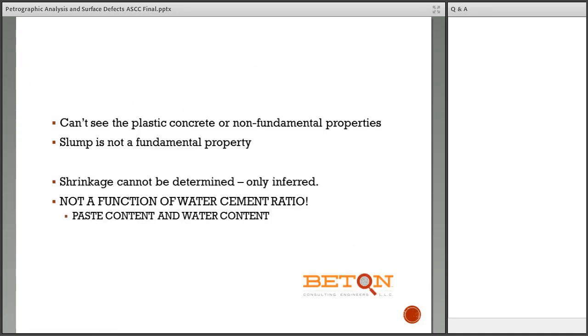So, one thing that the petrographer absolutely cannot do is tell you plastic or non-fundamental properties of the concrete. A perfect example is the slump. Slump is not a fundamental property. It's a property that changes with time. Strength is not a fundamental property. That's dependent on the geometry of the samples. But you can't look at the concrete and say that it was delivered in a blue truck any more than you could look at the concrete and say that it was delivered with a 7-inch slump. Water content and slump are long divorced and have been for at least a generation.